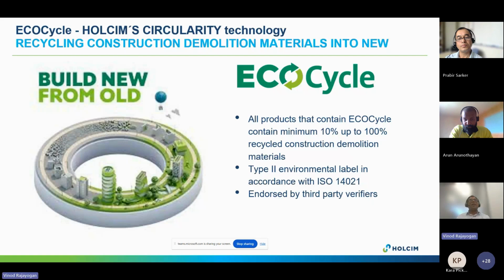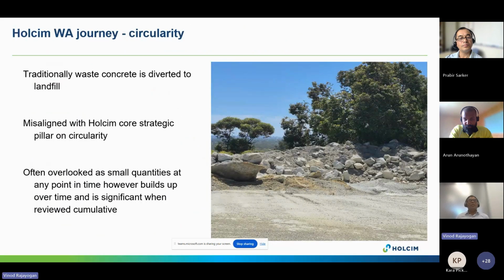What is the real problem we found? Over time, we found that our waste was generally being delivered to landfills. This is no different, I would say, in many industries, but this was very much misaligned with our strategic pillar on circularity. Often overlooked because it's such small quantities, but as it builds up, it was a challenge we took on to understand what we can do. Now, unlike crushed demolition waste, recycled return concrete often is not compacted. It may not even be cured adequately. And often there is a concern that this is different to C&D waste.